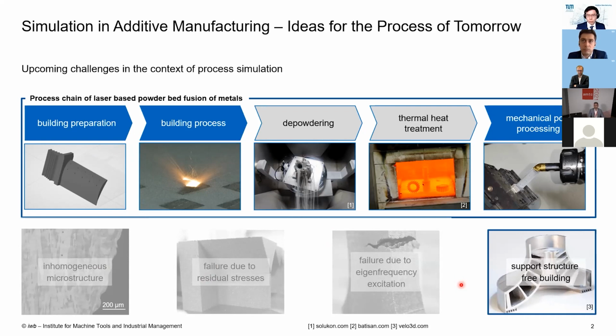Here it is the aim to enable a support-free manufacturing, and therefore a suitable process strategy is needed. So we definitely have to select suitable process parameters within the pre-processing step which are mainly influencing the cooling behavior of the components during the manufacturing process itself. And also there's a benefit for mechanical post-processing. So we have different advantages, for example, higher complexity for geometries that can be manufactured, and also reduced manufacturing time and costs due to the fact that we don't have to remove these support structures after the manufacturing process itself.